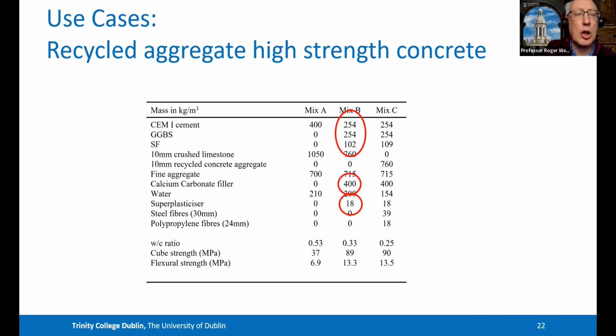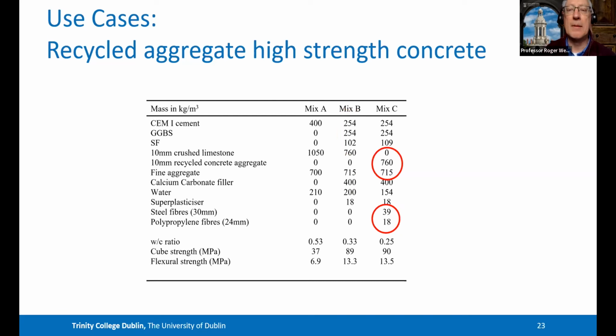about 60% recycled low carbon materials. And we've also used a filler here. If you see halfway down the page, we're using a calcium carbonate filler and a superplasticizer to give us the workability. So here now in mix C, again, we can get the same strength. We've managed to get a mix that does that. And we're replacing 100%. Now, you don't need to replace 100%, but we've replaced 100% of the aggregate with a recycled concrete where we selected it ourselves. In its previous life, this was 50 megapascal concrete. As we replace that, we put some steel fibers in. And as you can see, we can maintain a very high strength using 100% recycled concrete.